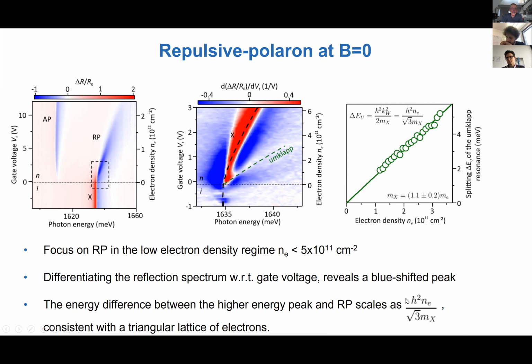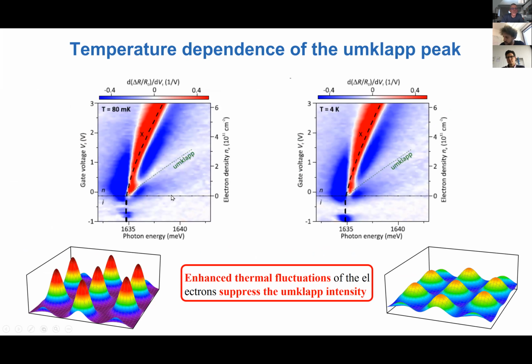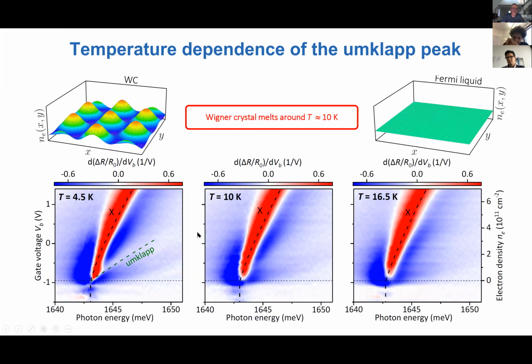So then the next thing we did is we wanted to look at the temperature dependence. This measurement was taken at 80 millikelvin, where the feature is relatively well developed. As we go to 4 Kelvin, we can still discern the umklapp peak, but presumably because of the thermal fluctuations, the electrons are not as well confined and the lines are broader and weaker. And as we increase the temperature further, above 10 Kelvin, you can see that the peak is completely gone. We have a thermal melting of the Wigner crystal at a temperature between 10 and 16 Kelvin.